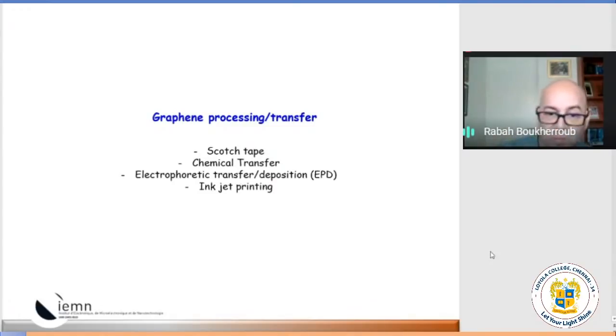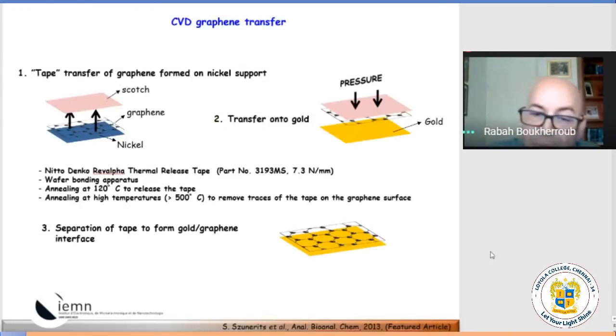I will cover mostly the Scotch tape and the electrophoretic deposition. Inkjet, I think you have seen everywhere, because here you're not limited by the number of layers. You don't care because you mostly make a very thick film, so that's not an issue. But I would really mostly focus on the techniques where you can control the number of layers you transfer to another substrate. The first one, as I told you, I will tell you why we want to use gold and why we're actually interested in gold modification with graphene.